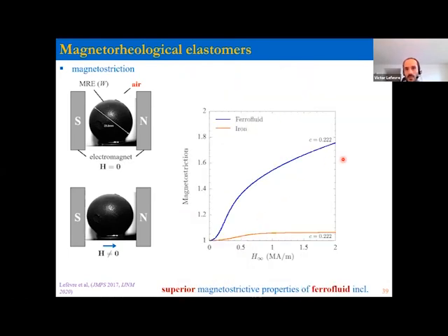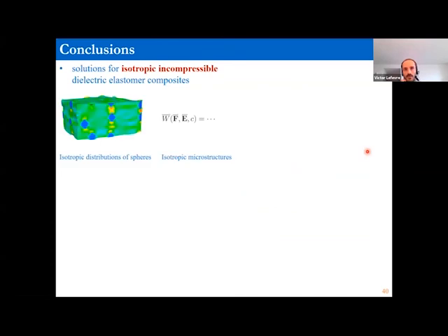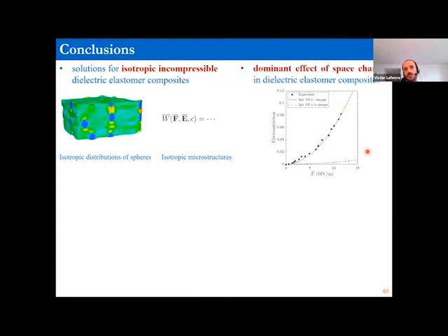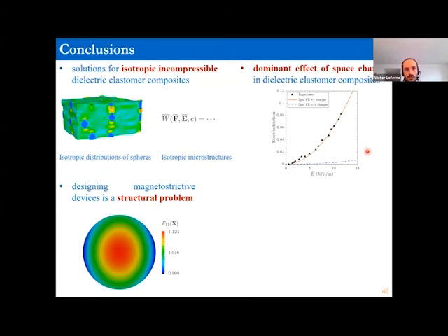And again, as I mentioned, you can see that the properties of the ferrofluid inclusions are much better in terms of the strain that you can induce in these materials. All right, so to wrap up, I've shown you these two solutions or three families of solutions that we obtained for dielectric elastomer composites. Two were numerics, the third one was analytical. And we use that to show the dominant effect of space charges in dielectric elastomer composites. And we use these solutions as well for the analogous problem of magnetorheological elastomers.